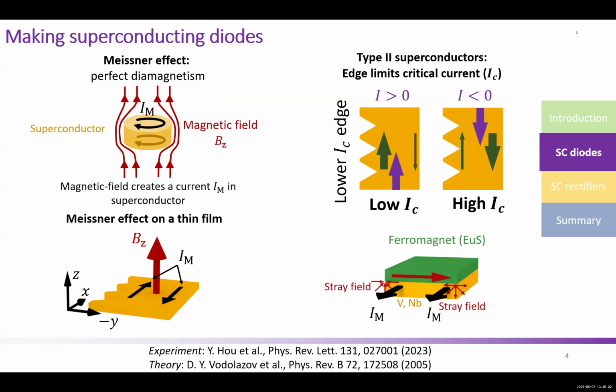We just place a ferromagnet on top of the superconductor, and now we have the stray fields from the ferromagnet which have opposite sign in both edges, but they actually result in having a Meissner current that has the same sign at both edges, because the very edge is what limits the critical current. This allows you to have a diode even at zero magnetic field. That is useful because it will not disturb other superconducting components working next to it.